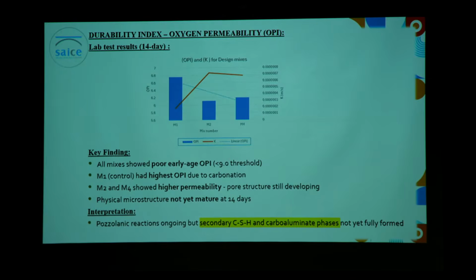Now, getting into the durability index results themselves, the key finding for that 14-day analysis period was that throughout all our mixes, there were generally poor results, particularly due to that 14-day analysis, because we normally wouldn't do a durability performance test for such a short period of time, but I'll explain as I go further for that analysis period. When we look at M1, the benchmark control mix, we saw it having the highest OPI due to carbonation.